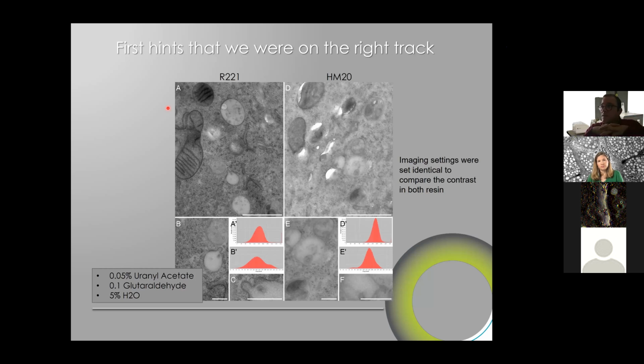And one day I was at the TEM, and then suddenly I had this kind of image under my eyes. And I was like, okay, I have the same imaging parameters as in the HM20 that I imaged a few minutes ago. And the contrast is significantly higher. The image is also a bit darker. So I was kind of, okay, is it because I did not focus the beam where I had some changes and so on? And looking at it carefully, it seemed that the contrast was much higher. And when we looked at the histogram, basically it's more spread. So basically we have a wider range of contrast for the same number of counts. And so that was the first time that we had an idea that somehow the resin was more contrasting with the same conditions.